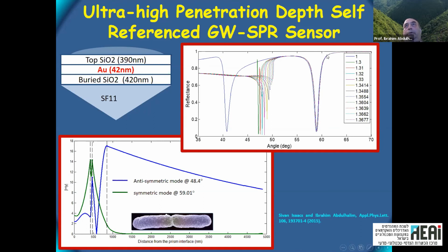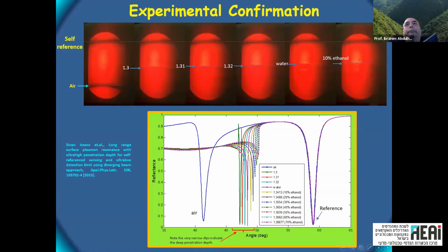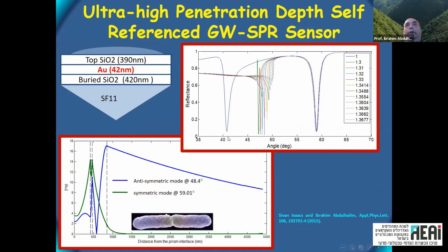Besides, this sensor is self-referenced, so this peak, this resonance, which corresponds to this interface, does not move as you change the refractive index. So you can use it as a reference. And for the air, you still can see the resonance. So you can measure gases, liquids. It's self-referenced. Here it becomes very narrow. So you get improvement of the figure of merit, and you can control the penetration depth.